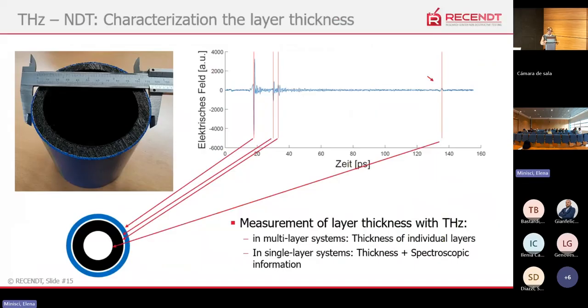Here I have an example of how we can detect the layer thickness with the terahertz signal. We use the time signal where we have the front layer, then the next terahertz pulse reflection coming back from the second layer, then there is a little air gap between. In this case, we could also detect some delaminations, and then the last layer. In this case we have a multi-layer, so we can image the different layers. But if we have only a single layer, we can also get the spectroscopic information, the chemical fingerprint of the polymer or of other chemicals inside.